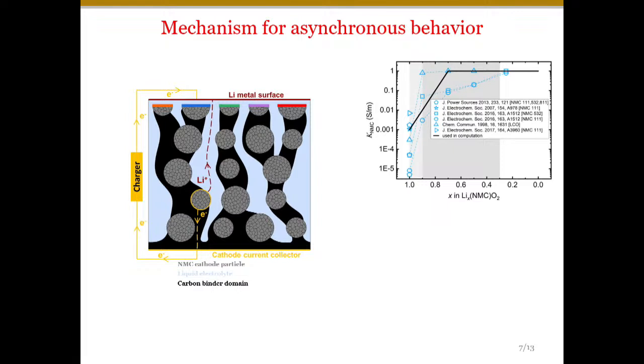If you look here, the black is our carbon binder domain, which is electrically conductive. The gray are our NMC active material particles, and we have 5 particles going from left to right. They have increased electrical resistivity due to the NMC particle, which breaks down the continuous carbon binder network.